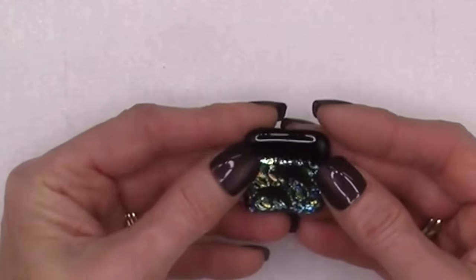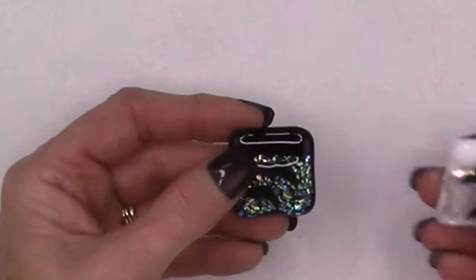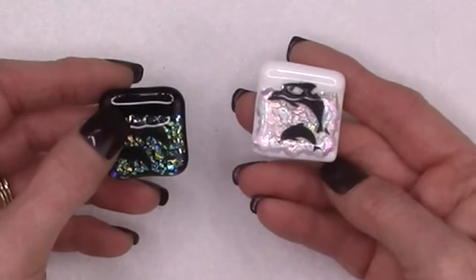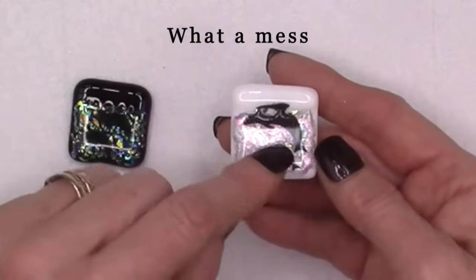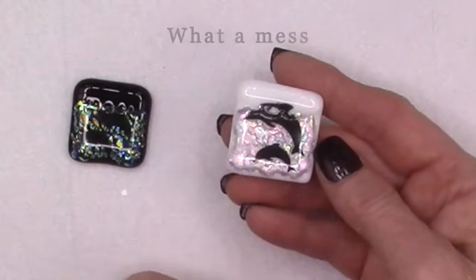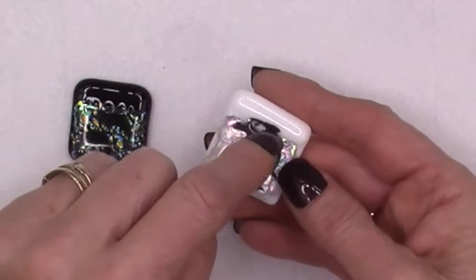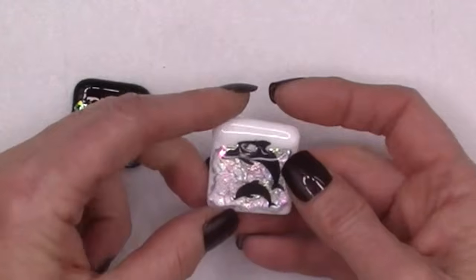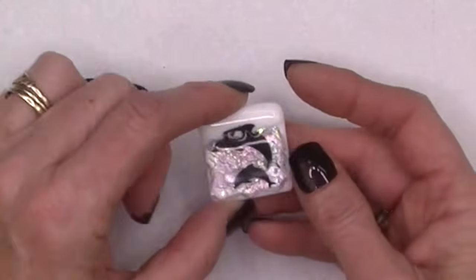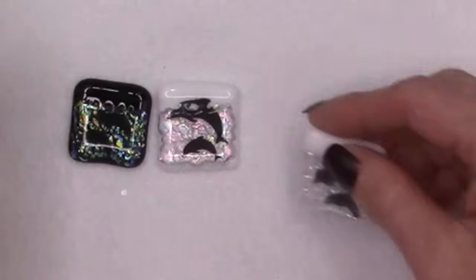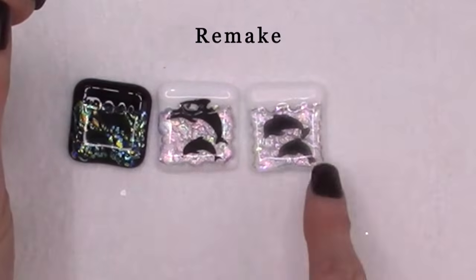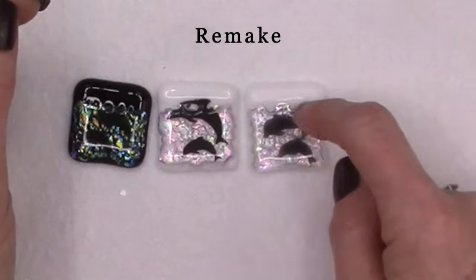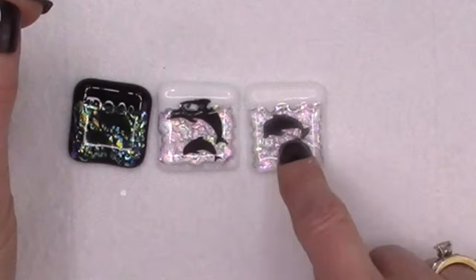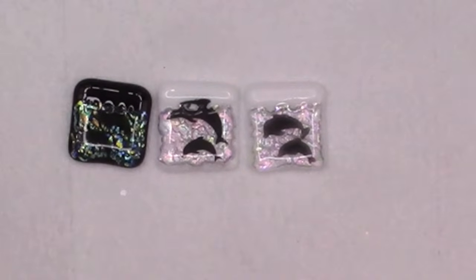Very subtle, but the white one didn't turn out so good. Look at that. Remember, I put the decal up over the white and it actually split. I tried to put it into the crevice there and it split. So what I did was make a second piece, and I didn't put the dolphin into the crevice. I kept it on the clear side of the dichro when I fired it, and that turned out much better.